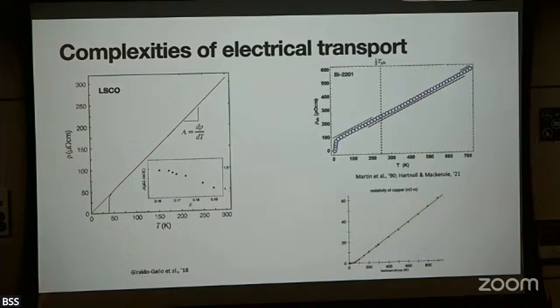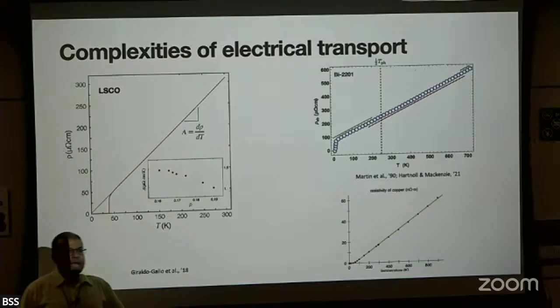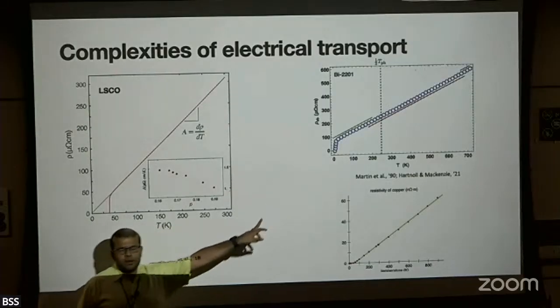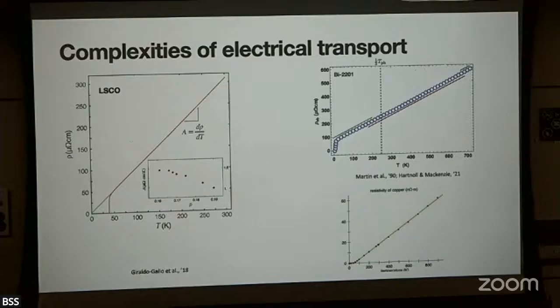In Dmitry Maslov's talk, he already talked about electron-phonon scattering, and that's basically what is causing the T-linear resistivity in copper. The basic idea being, if you're above some characteristic temperature scale, which for electron-phonon scattering is set by the effective Debye energy scale or some Bloch-Grüneisen scale, the phonons are effectively classical. The phonons have an unbounded Hilbert space. You can describe their occupation in terms of the Bose-Einstein distribution. When the temperatures are larger than omega Debye, you can just keep exciting more and more phonons, right? So it effectively acts almost like a source of quasi-elastic scattering, and that is what gives you this T-linear resistivity, okay?